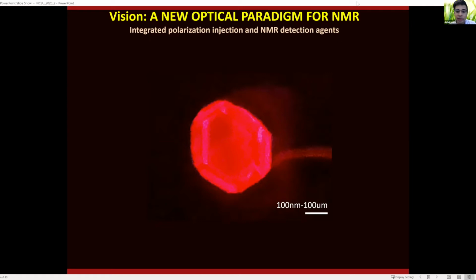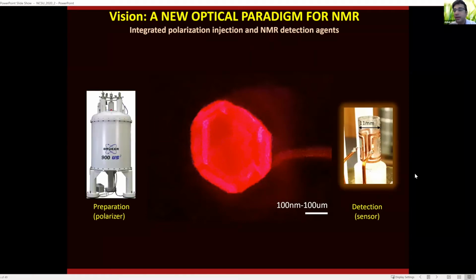And this relies on some sort of special nanoparticles of wide bandgap semiconductor materials, and I'll show you how. But a classic example is diamond. This is a nanoparticle of diamond. And so it turns out that, quite interestingly, because of the properties of this material, you can take this material and make it appear as if it was a polarizer. So it plays the role of a large magnet as well as a detector or an RF coil in an NMR experiment, and you can address this with light.